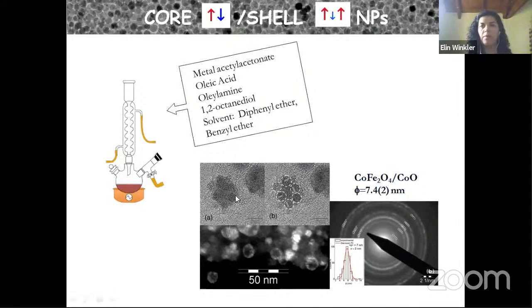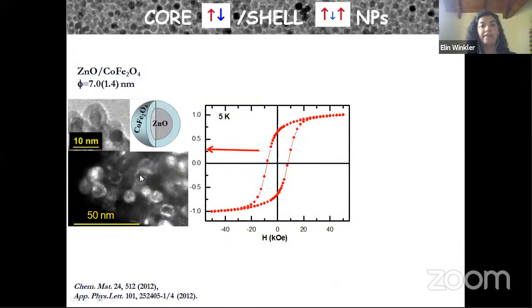Then we are going to see many more STEM images. In this case, as the mismatch between these two phases is large, the shell overgrows like small nanograins over the core. And this is a transmission electron microscopy image where the shell is the bright phase, the cobalt ferrite. This image is reconstructed with the electron diffraction that came from the diffraction rings of the cobalt ferrite. So the bright image corresponds to the cobalt ferrite. So here are the results.